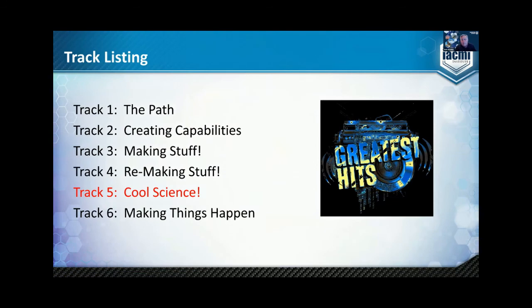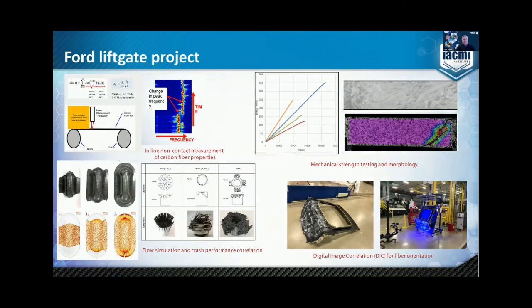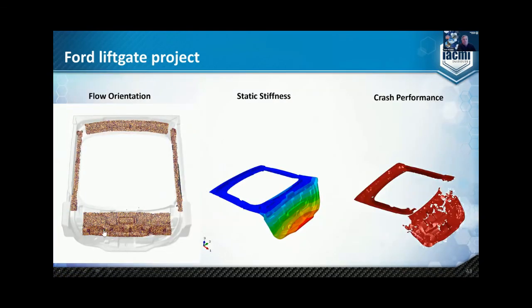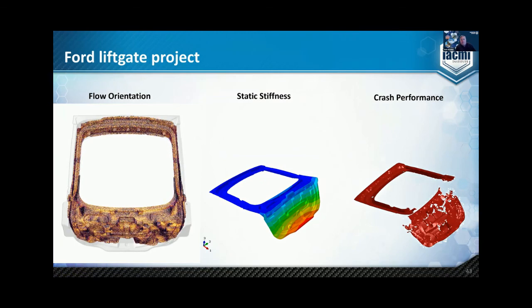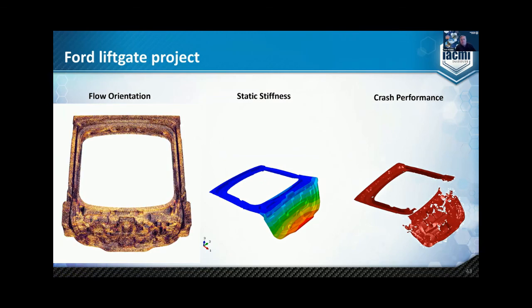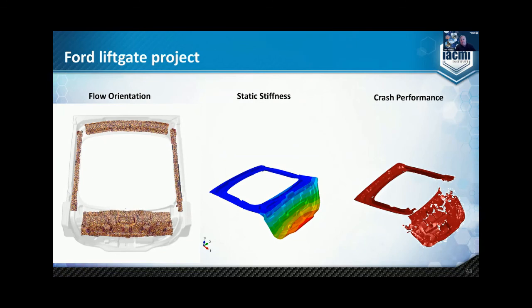All this has included a bunch of cool science. It included, for example, on the liftgate project, flow studies, non-contact measurement of fiber density, certainly crash performance correlation, digital image correlation for that fiber orientation after the molding. You see here the modeling simulation of that platelet prepreg SMC being molded. That informs the static stiffness and, of course, the crash performance of the part.